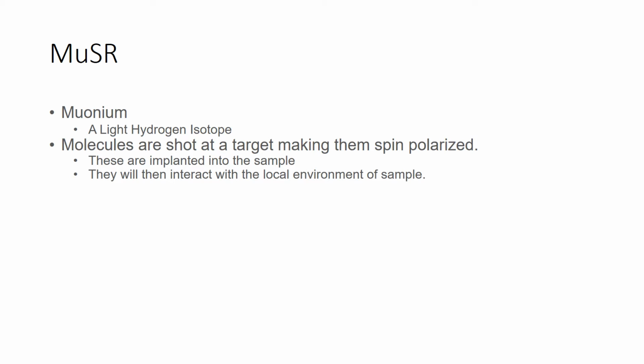In our case, the sample was a cadmium oxide powder. When they're implanted into the sample, they can then interact with the local environment of the sample and the different nuclear moments within the sample.